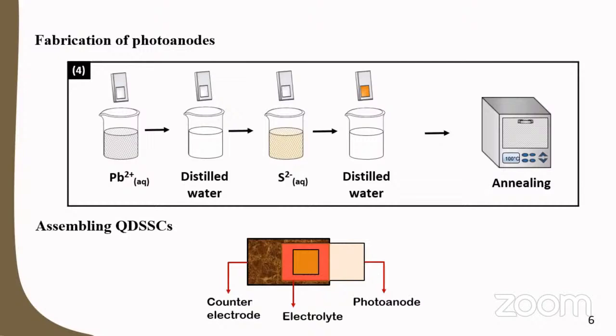Finally, the photovoltaic device was completed by clipping the prepared photoanode together with the copper sulfide counter electrode, prepared by depositing copper sulfide on a brass plate, and injecting polysulfide electrolyte in between them. And for a comparative study, another set of photoanodes were prepared by doctor blading TiO2 P25 paste on TiO2 P90 instead of the TiO2 nanofiber layer.